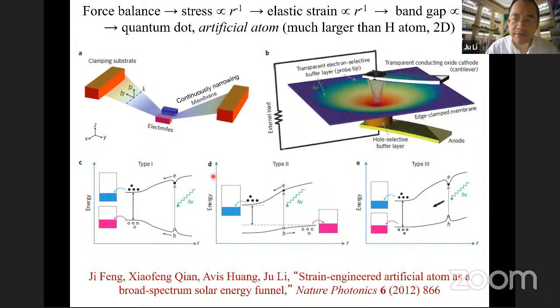And then you would have basically a quantum dot, if your band alignment shifts as 1 over R, which would be like a hydrogen atom. But it would be a 2-dimensional hydrogen atom, that's first. And also it could be much bigger. It could be a few microns. It can be much bigger than a real hydrogen atom. So we call that an artificial atom.